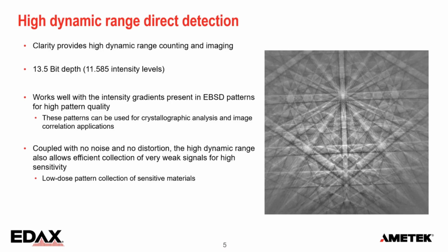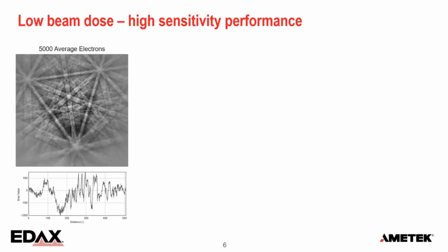The second type of application, and that's what I want to focus on a little bit more in this presentation, is that we don't need to capture this many intensity levels, of course. When we just have a few gray levels, it may already be enough to identify the bands in our diffraction pattern. And that allows for low dose pattern collection of these sensitive materials.